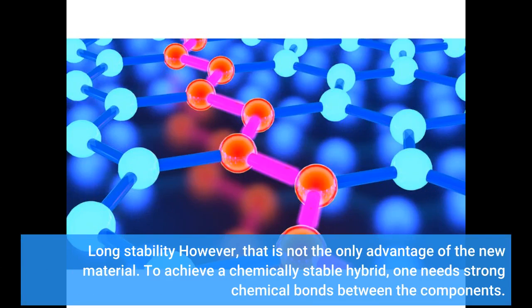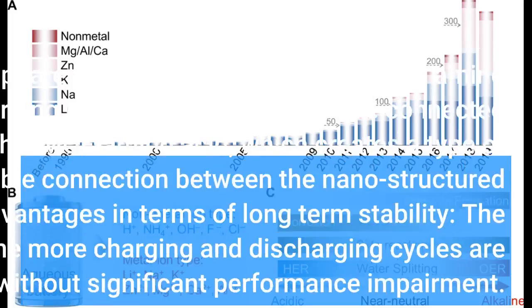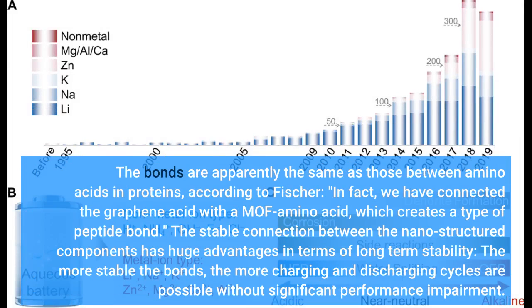Long stability. However, that is not the only advantage of the new material. To achieve a chemically stable hybrid, one needs strong chemical bonds between the components. The bonds are apparently the same as those between amino acids in proteins. According to Fischer, in fact, we have connected the graphene acid with a MOF amino acid, which creates a type of peptide bond. The stable connection between the nanostructured components has huge advantages in terms of durability.